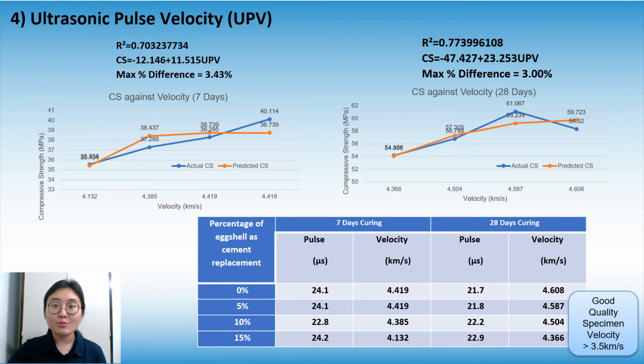The last test conducted was the UPV test. The results obtained from the UPV were tabulated and all of the velocities obtained, which were more than 3.5 km per second, show that the specimens were rated as good quality. With the same regression method used, R-square value was obtained from the correlation between the compressive strength and the ultrasonic pulse velocity test. The R-square value was lower than 0.8, which means that it was a medium correlation between the compressive strength and the UPV test. The maximum percentage difference was about 3%, which is much higher than the rebound hammer percentage difference, which is only 1%.